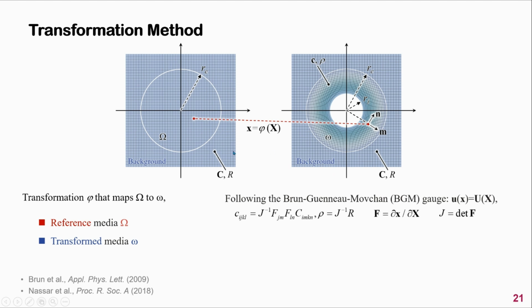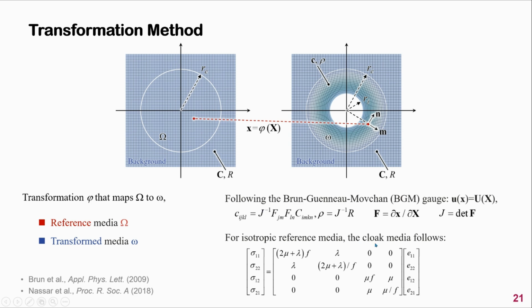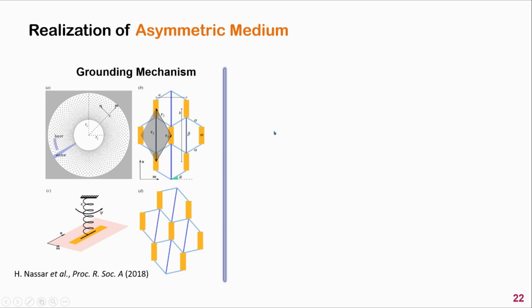governing equation. For example, let's consider that the background media is isotropic. The constitutive relation of the cloak media will be as follows. Generally, as can be seen here, since these two components are not equal to each other, the elasticity tensor of the transformed media will no longer exhibit minor symmetry. That's why we call the transformed media asymmetric. To achieve such an asymmetric media, the core idea revolves around applying a carefully engineered distribution of body torque to modify the balance of angular momentum.